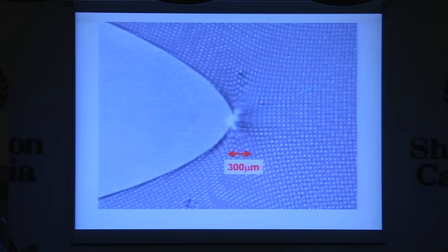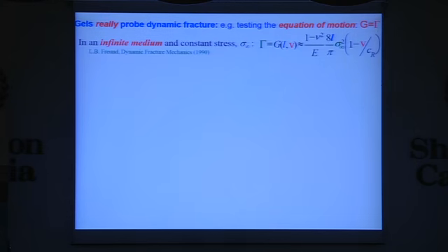Here you can see the grid. So we have a 50 by 50 micron grid along the path of the crack, and we can use the deformation of that grid to actually back out the entire strain fields, the strain tensor at the tip of the crack, as it's running at dynamic velocity. This is one thing you can do when you break jello that you couldn't dream of doing when breaking tool steel or glass or anything, just because it's relatively slow.